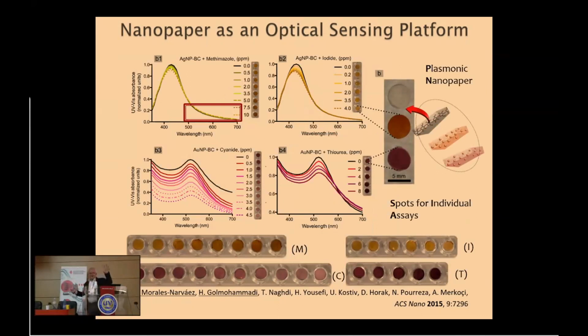What happens is that these compounds specifically corrode nanoparticles because there is some interaction chemistry there. And if you corrode the nanoparticles, you change the size of nanoparticles, you totally change the optical properties of nanoparticles. So the plasmonics is going to change, and you see here these curves corresponding to the optical response of the sensor are changing with the different concentrations of this compound. You see here clear changes of the color. So we have this simple piece of paper able to detect these different compounds.